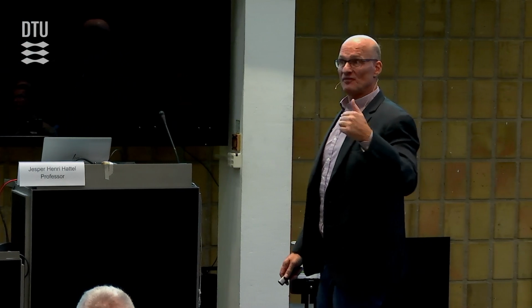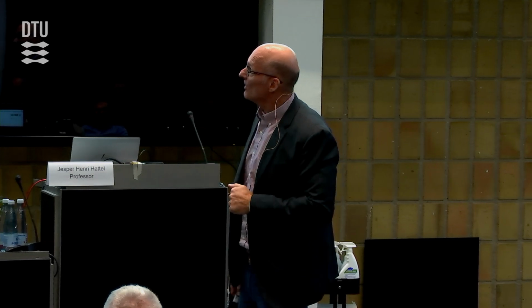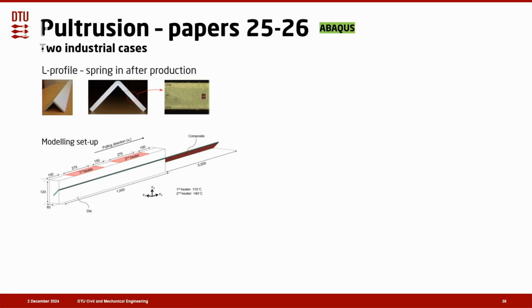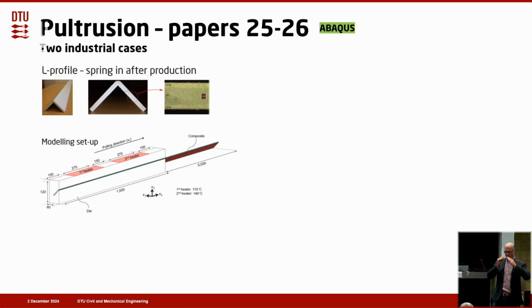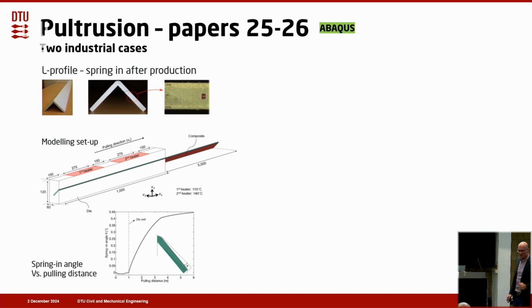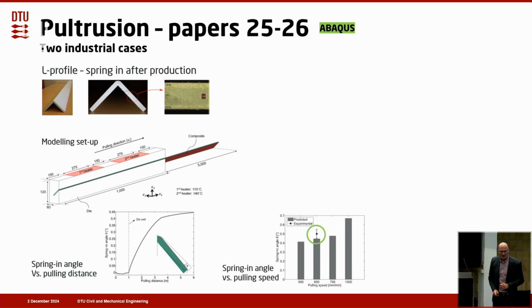These models were used for two industrial cases. The first one is this L profile. The problem with this L profile is that when it's pulled out of the die, it has spring-in. So it deforms inwards. And we were able to predict that with our model. You see here it deforms a little inwards. And then when we compared with an experimental finding, we actually got very good results.